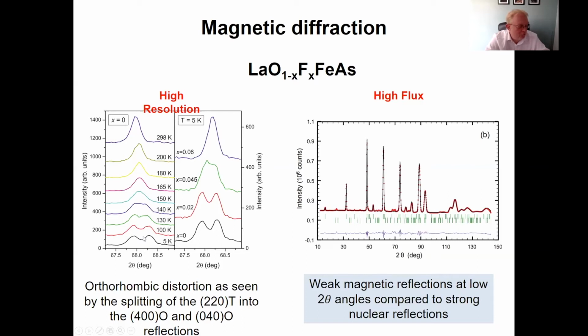And this is an orthorhombic distortion, splitting this line into two lines from a tetragonal to orthorhombic, because we're starting to create a magnetic structure within the material, which changes the space group of the material. On the other side, we've got a constant temperature. Now we're changing the value of X, and we see the same thing.